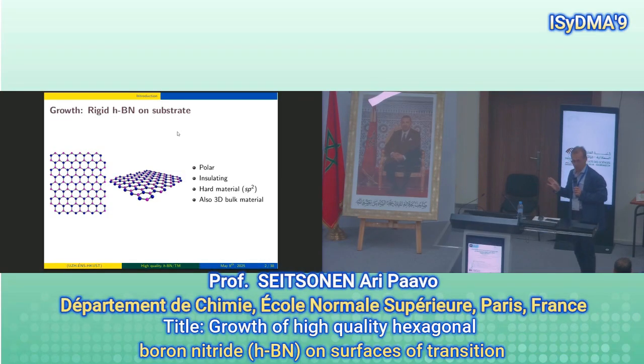So the HBN, maybe you know already the properties. It's a polar material, of course, boron and nitrogen. They have different electronegativity, but it's insulating. It has a large band gap. So although the structure looks exactly the same as graphene, because you have these alternating atoms or elements, and you have the polarity, there's a band gap. So this material is insulating, and it is being used as a dielectric insulator. For example, in this case, we have something on a transition metal, so we put HBN in between to isolate, for example, an adsorbed molecule from the electronic structure of the metal beneath. So that's one of the roles of HBN.